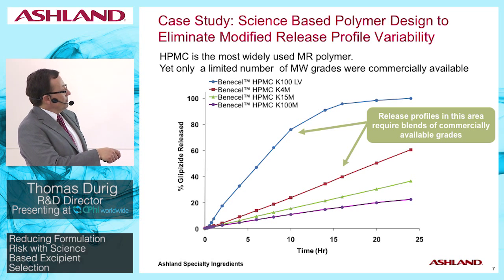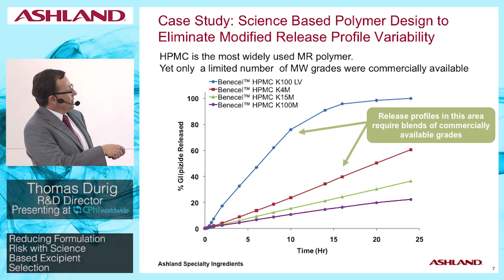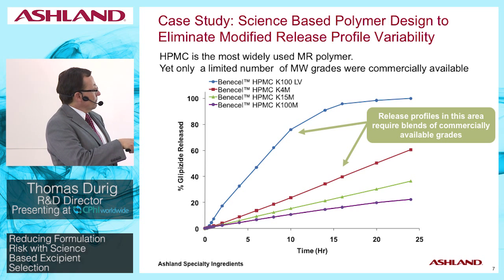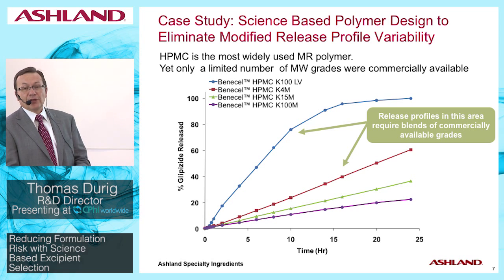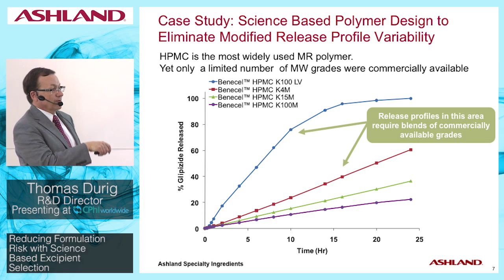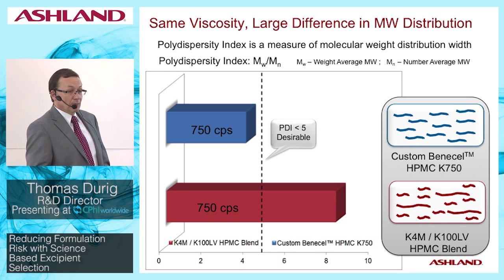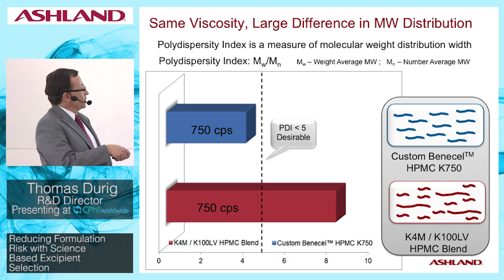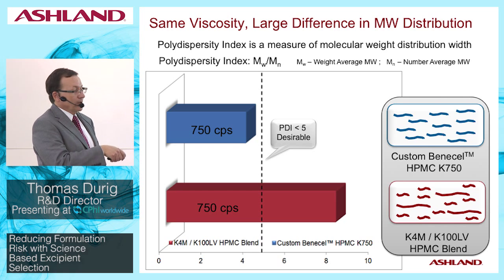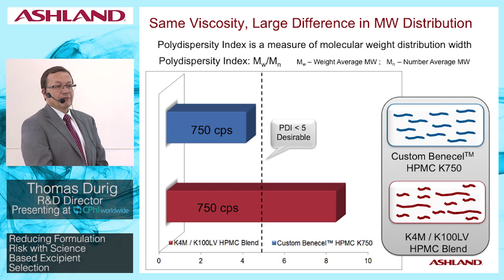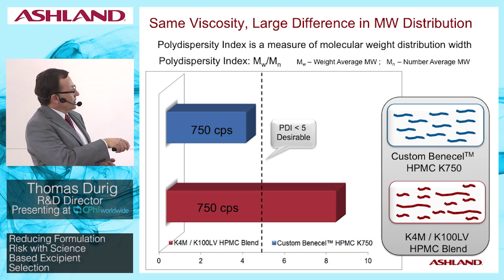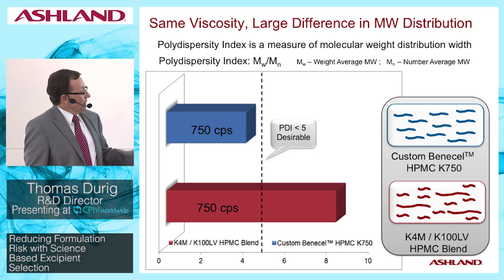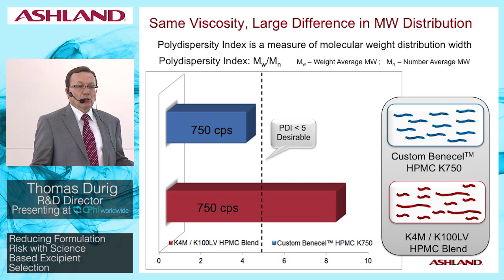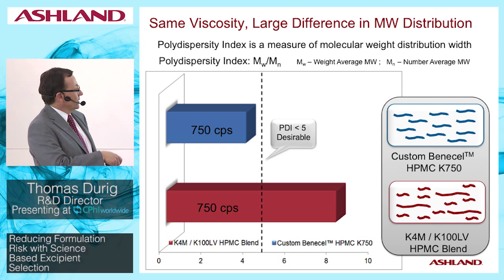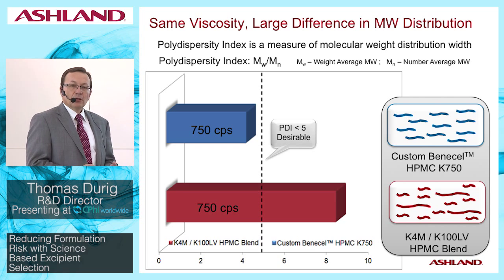Most likely, the option would be to do the logical thing and try a blend of the blue one here, which happens to be 100 centipoise HPMC, and blend that with this red one here, which is Benecel HPMC K4M, 4000 CPS. And maybe we would achieve an intermediate viscosity grade, giving us an intermediate release. But there's a significant problem with that, because although we can essentially blend a 100 centipoise HPMC with a 4,000 centipoise HPMC to make an intermediate 750 centipoise HPMC blend, what we're in effect doing, as you can see here in the bottom left corner, is blending essentially short polymer chains and long polymer chains to arrive at some intermediate viscosity, which as a result has a very wide bimodal molecular weight distribution.